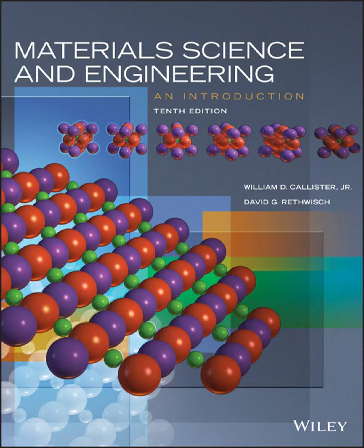Exactly. And that migration of atoms of one metal into another, that's what we call interdiffusion, or sometimes impurity diffusion. It's where you see that net movement from high concentration to low concentration. But interestingly, diffusion also happens in pure metals. Atoms of the same type swap places. That's self-diffusion. You can't see it by looking, of course, because the composition stays the same. But it's happening constantly. And understanding these diffusion rates, both types, is just crucial for engineers. It lets them predict how materials will behave during heat treatments. They can enhance properties deliberately, or sometimes slow down processes they don't want, things that might degrade the material.